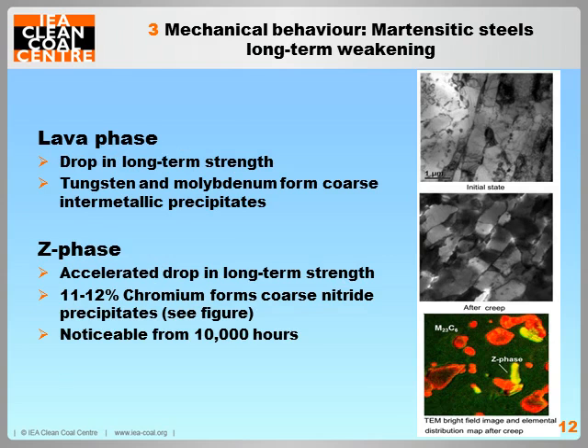So martensitic steels suffer from long-term weakening mechanisms. With all chromium martensitic steels with 9 to 12% chromium, the tungsten and molybdenum will precipitate out as large and coarse Laves phase, which consume all the small strengthening precipitates. Due to Laves phase weakening, P92 has been found to have long-term creep strength not much greater than P91.